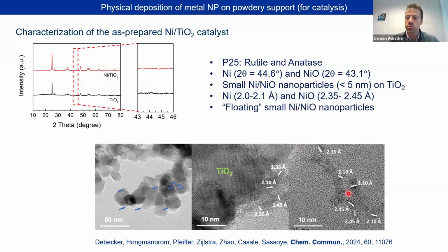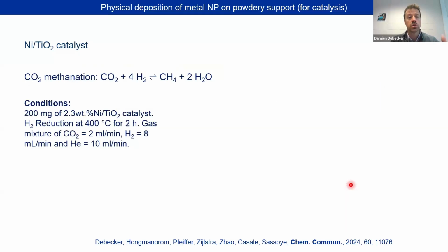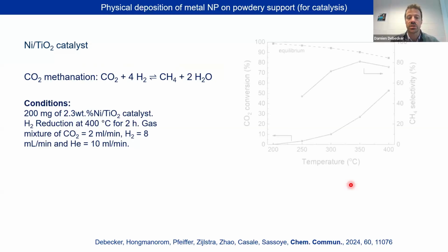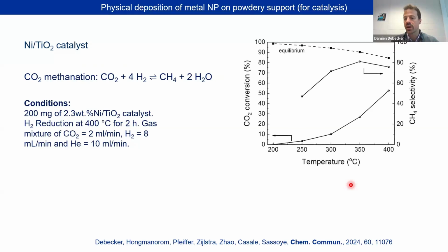Unfortunately, in this case, we also saw nickel particles that we call floating particles, which are not in touch with the support. All those here are in touch with the support, those ones not. So that's a problem, because we want to disperse them on the support. In some cases, for part of them, it's not the case. They are floating separately. So we tested these kinds of catalysts in CO2 methanation, and readily they are quite active.